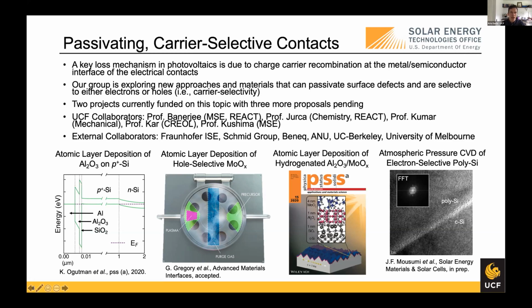So if you combine that high quality passivation, so passivating these interface defects that prevents recombination, and then excellent carrier selectivity, you can really elevate the ceiling in terms of the maximum efficiency you can provide for a solar cell. So that's the general concept.